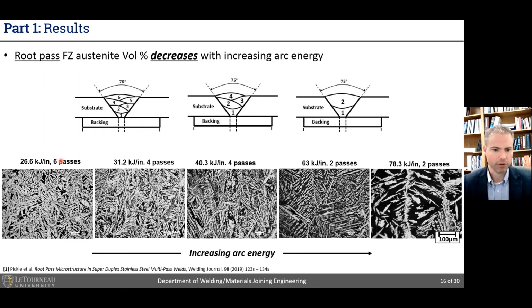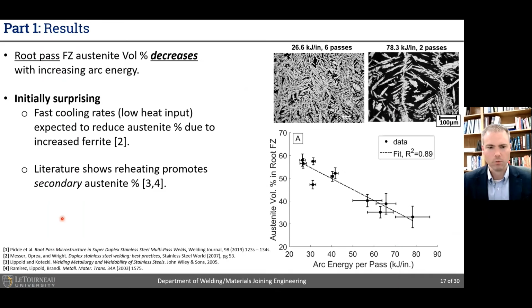So in our first findings, we looked at the microstructures for increasing arc energy, and what we saw was opposite of what we expected. From the literature, we expect that high heat input will result in slow cooling rates, which ought to result in higher austenite contents. But we found exactly the opposite, and this was the beginning of our starting point for the rest of the study, to try to understand why it is that we see so much more austenite in the root pass. We plotted the percent austenite as a function of arc energy.